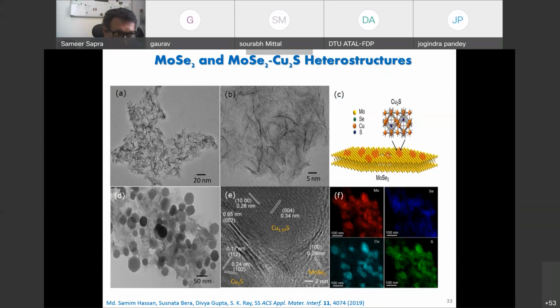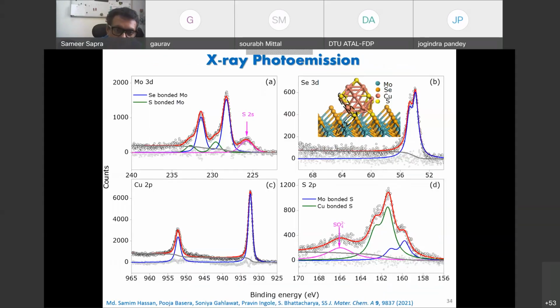And that is also evident from the fact when you look at the X-ray photoemission spectrum of these materials, that molybdenum, you'll see two different signals, one from the molybdenum selenide and the other from molybdenum sulfur bond, which is from the DDT that is coming in. And one signal for selenium, one signal for copper. So selenium is bonded only to molybdenum, copper is bonded only to sulfur, and sulfur again has two signals over here, one bonded to molybdenum and one bonded to copper. Well, a bit of sulfur does get oxidized in the process because it is on the surface. And I have always told you that chalcogenides are prone to oxidation. Okay.